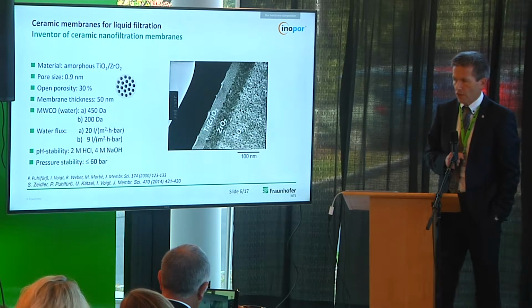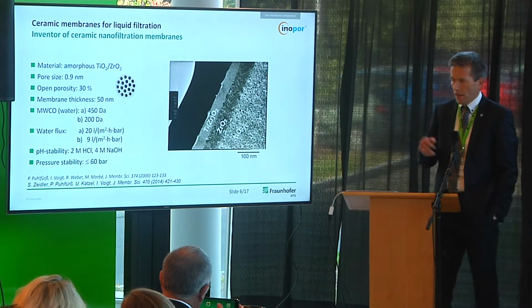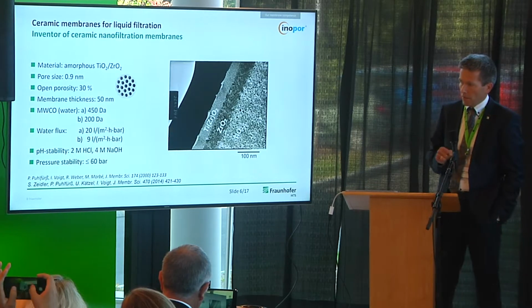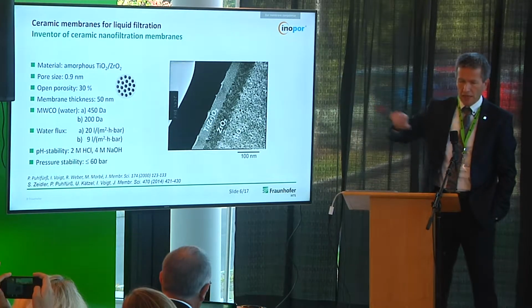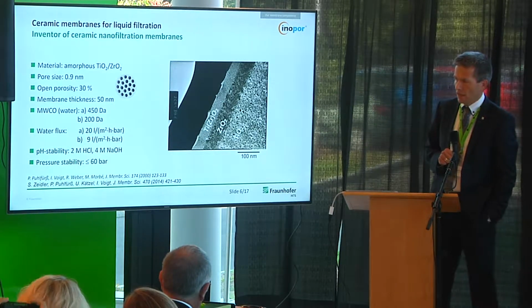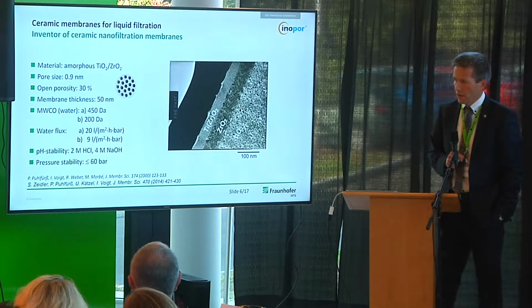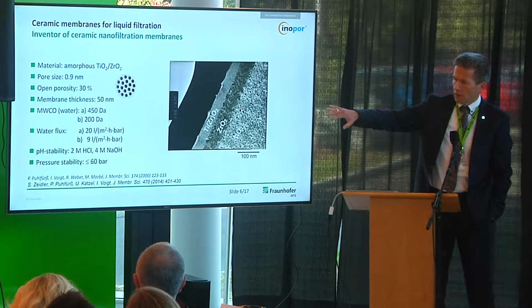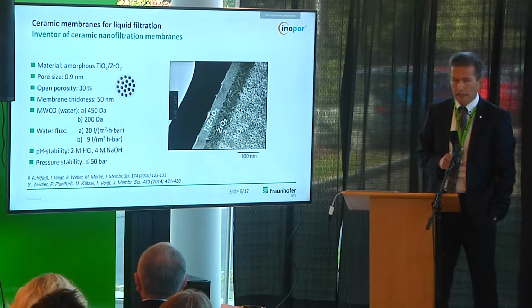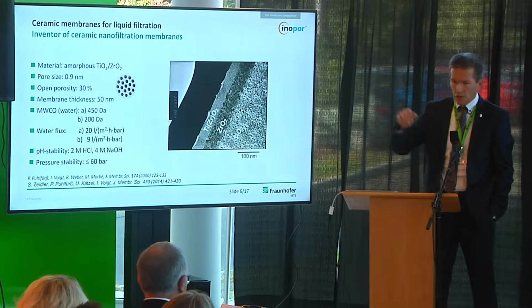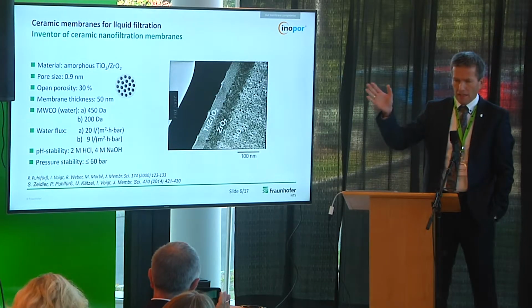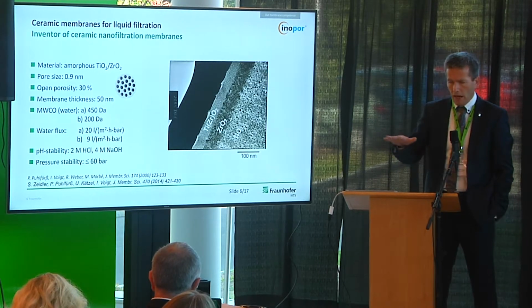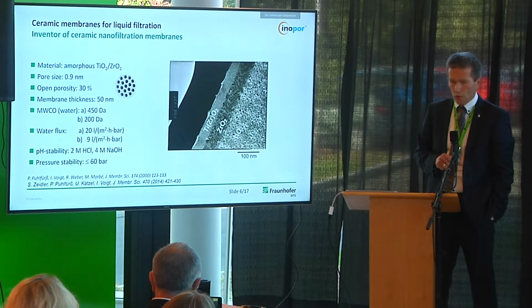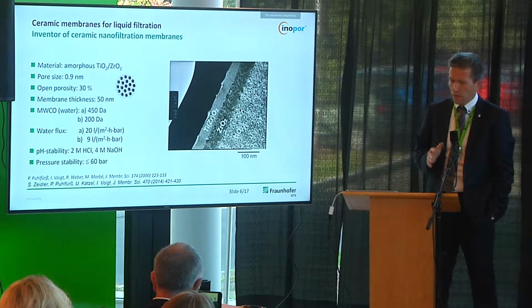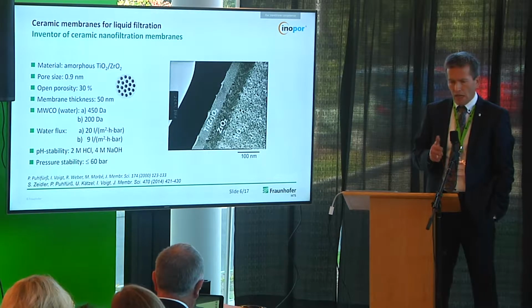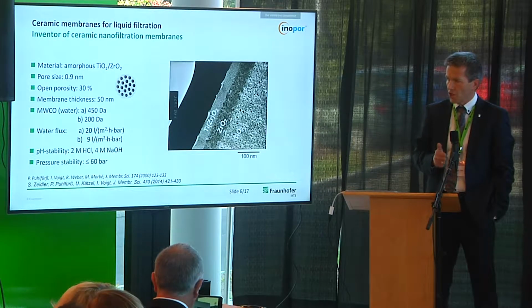Water flux is in the range of 20 liter per square meter hour and bar, as well as 9 liter per square meter hour and bar. The membrane itself is a very thin layer of titania with a small portion of zirconia on top of a mesoporous zirconia and titania interlayer. And you can imagine that to prepare these thin membranes in hundreds of square meters, you have to run the preparation under very controlled conditions.